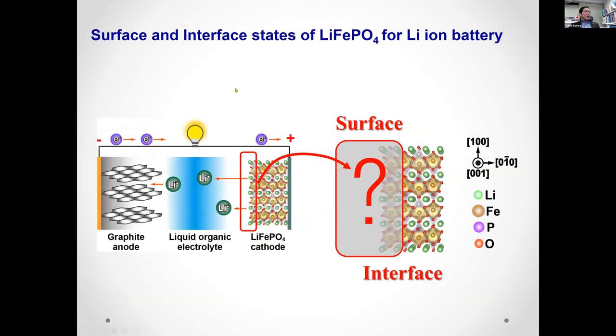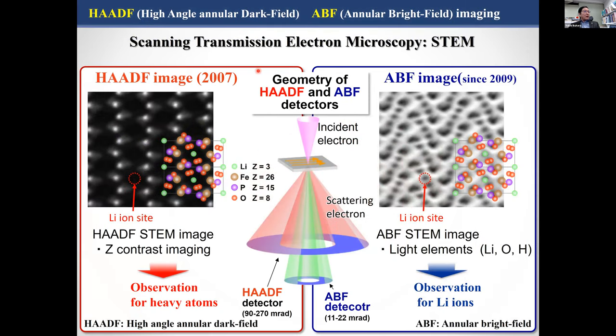This shows a schematic of the surface and the interface of iron olivine for lithium batteries. The olivine is used for cathode and graphite anode, and during charging, discharging, lithium is dissociated to form the dissociated interface. I'll just use this laser pointer. This is the dissociated interface, okay? And the surface is here. Therefore, surface and dissociated interface structure is very important to understand the mechanism of the charging, discharging phenomena. We applied the HAADF-STEM and ABF-STEM imaging techniques to characterize these materials.